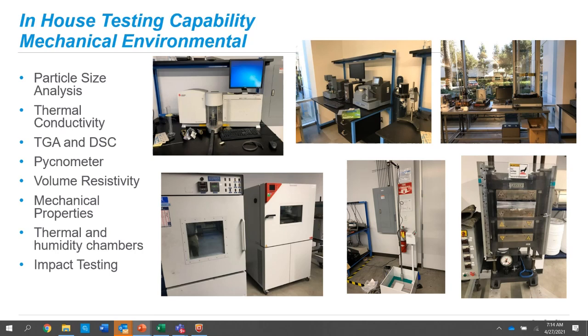We certainly do mechanical testing, tensile, elongation, tear. As I said earlier, environmental cycling and humidity testing is very important. And then for the radome work we're doing a lot of impact testing. So we're evaluating new thermoplastics. We're adding tougheners to them to improve the abrasion or the impact resistance. We're worried about hail strike. We're worried about rain for these radomes, and so the performance of those under an impact load is very important. It's a very dramatic test too. It's a 500-gram ball that drops on the panel from anywhere from 1.5 to 2 meters, and if it shatters, it can create a mess.